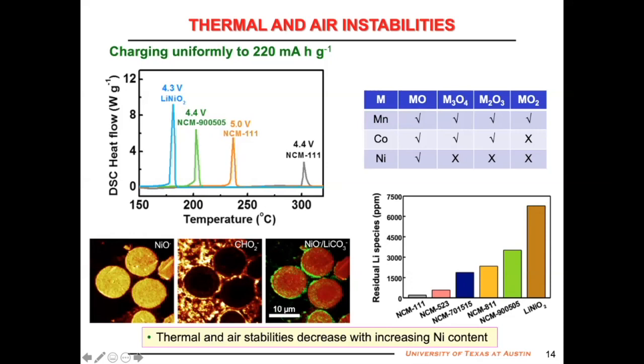In addition to that, the biggest headache in the industry with high nickel compounds is that lithium comes out to the surface when you keep the material at ambient condition in air to form lithium hydroxide or lithium bicarbonate or lithium carbonate, as you see here, these little green things. That's called residual lithium. If you have too much of it, it creates problems, clogging, to make electrode. It also degrades the performance. So residual lithium increases exponentially with increasing nickel content. When you go from 60 to 80, already a problem, 80 to 90, much more problem, 90 to 95, even more, 95 to 100%, much more.